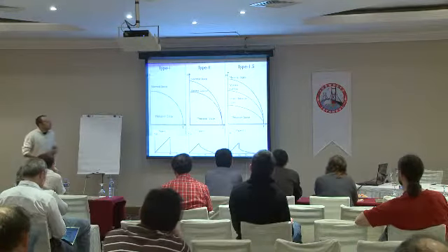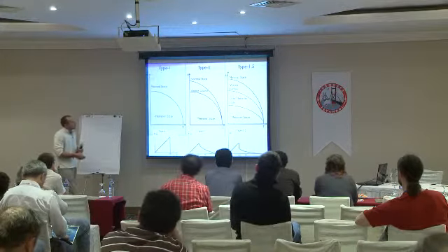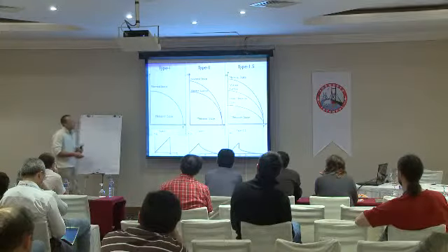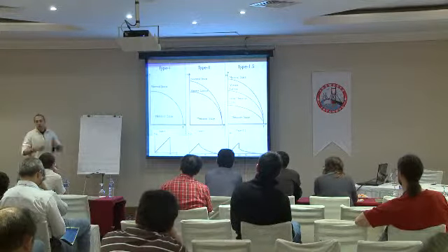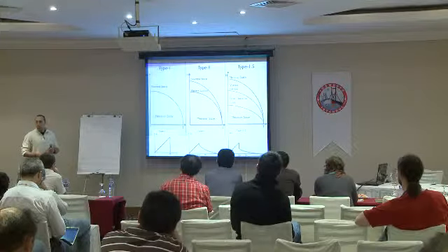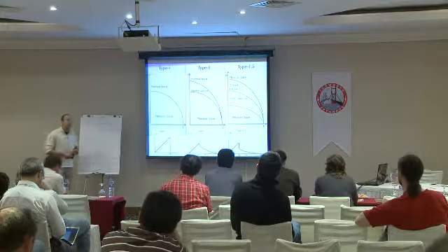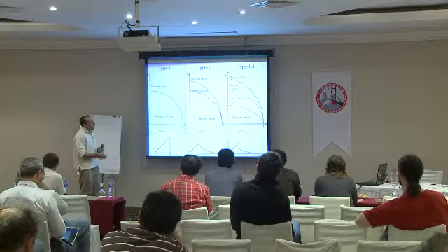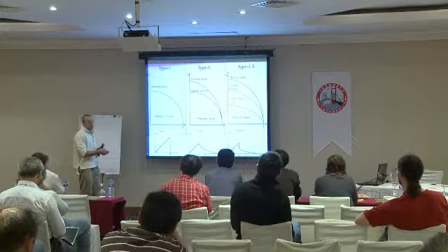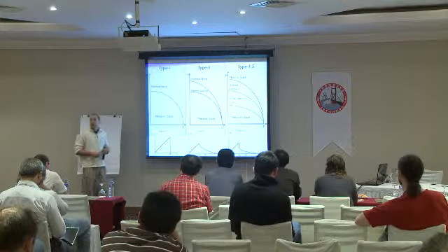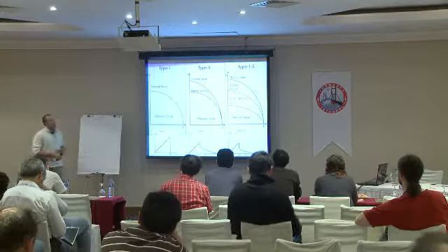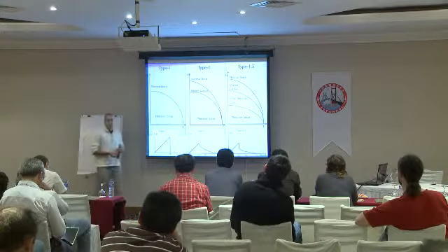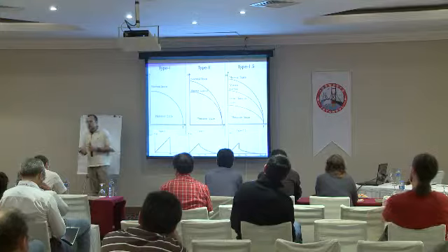So correspondingly, the phase diagram in general will acquire an additional phase where vortices clump together because of this long-range attractive interaction. The system has the Meissner state in low magnetic field. It has vortices when you have very high magnetic field, and in between it allows a macroscopic phase separation into domains of Meissner and vortex states.